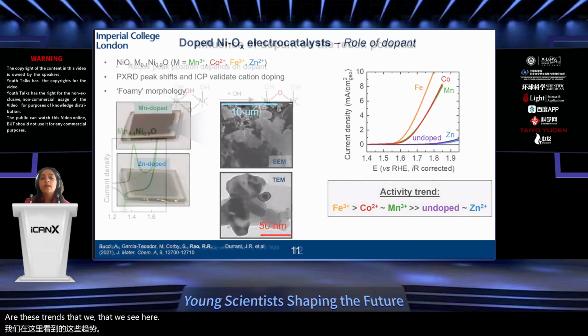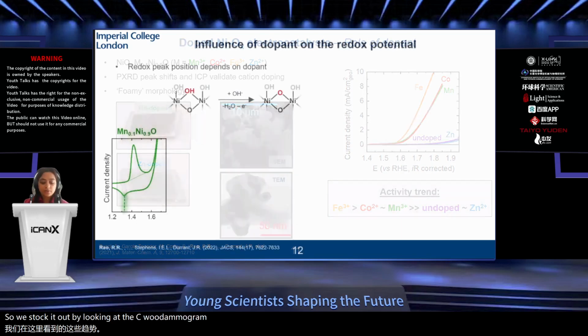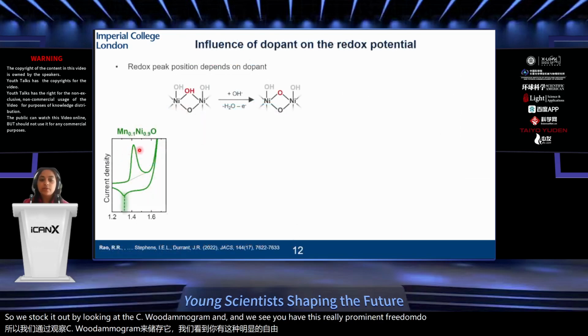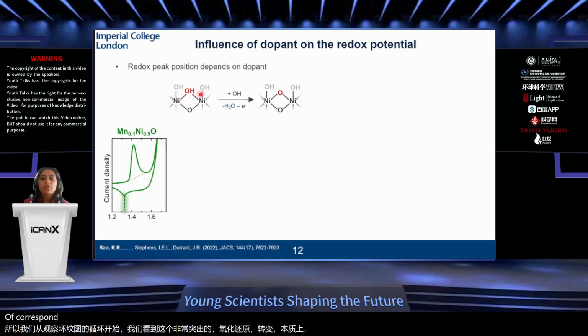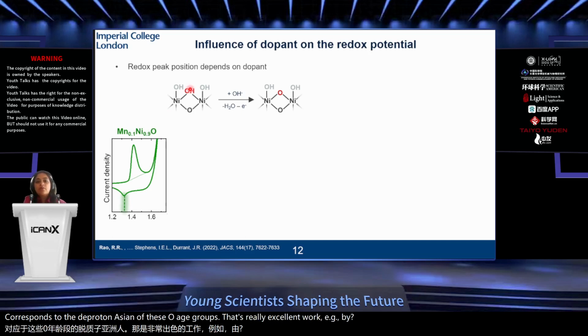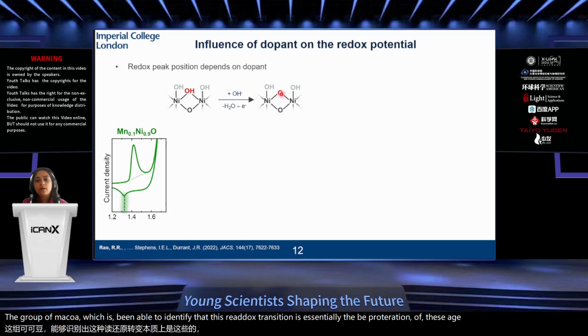So we started out by looking at the cyclic voltammogram, and we see we have this really prominent redox transition, which essentially corresponds to the deprotonation of these OH groups. There's really excellent work, for example, by the group of Mark Koper, which has been able to identify that this redox transition is essentially the deprotonation of these OH groups to form these oxo groups on the surface.